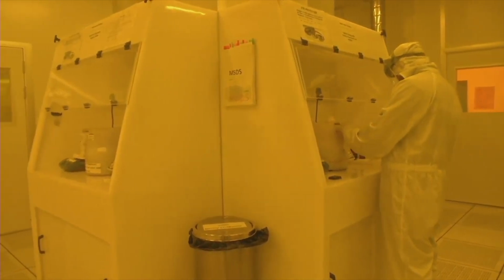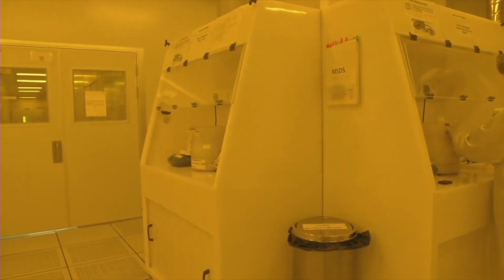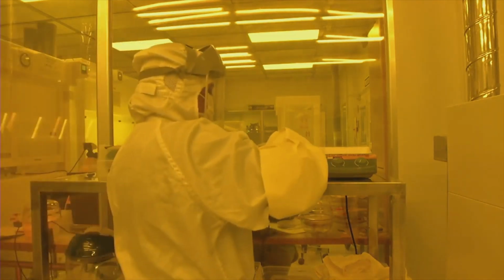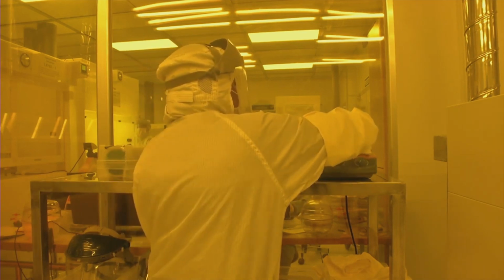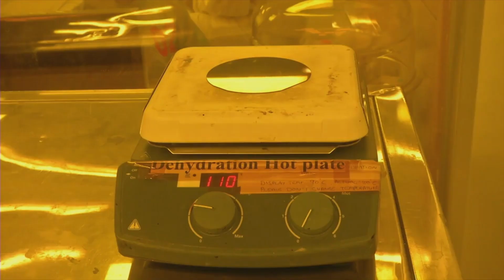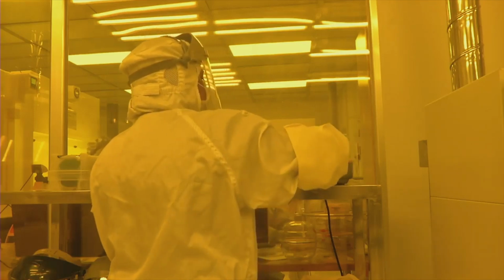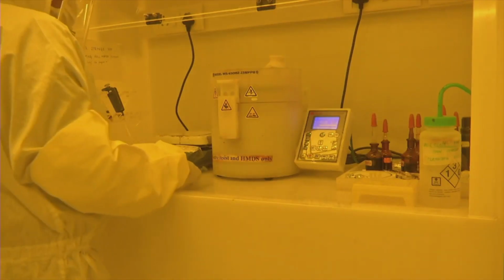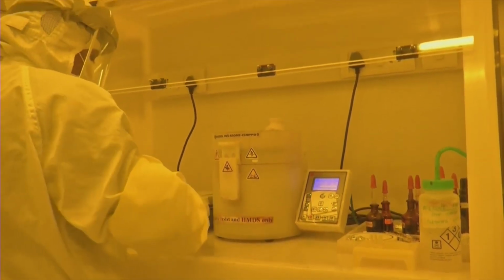So the next step is to coat the wafer. Before coating it, we have to dry the wafer. So the first step is a dehydration bake. We want to remove any water that is sitting on the wafer using a dehydration bake, and that is done using a hot plate. So we place the wafer on the hot plate, which is maintained at around 110 degrees C. This is slightly above the boiling point of water, so that all the water present on the wafer is evaporated. After evaporation, we now have a dehydrated wafer, and now the wafer is taken for coating.